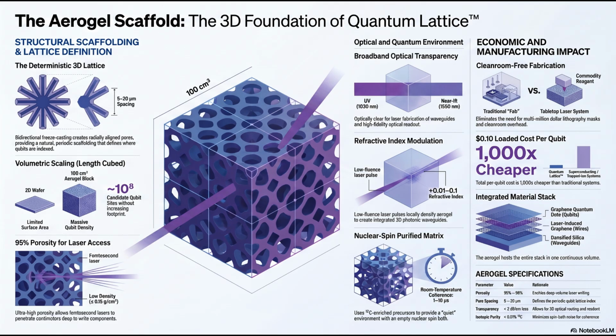If they drop it in liquid nitrogen at 77 Kelvin, the coherence jumps to 50 to 500 microseconds. But if they place it in a standard liquid helium cryostat at 4 Kelvin, the electron spins freeze out almost all remaining phonon interactions, which are physical vibrations in the lattice. The coherence time leaps to a massive 0.5 to 5 milliseconds. So at 4 Kelvin, the qubit state survives for 5,000 microseconds.